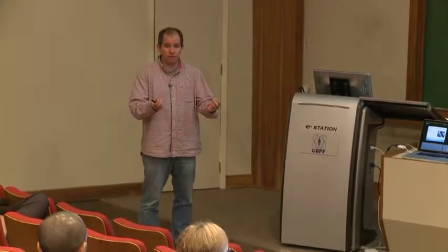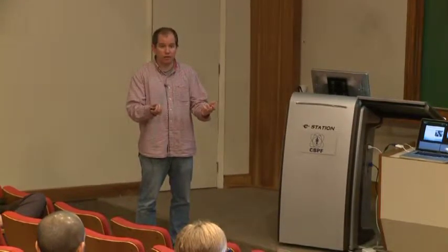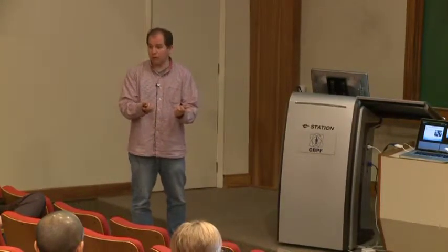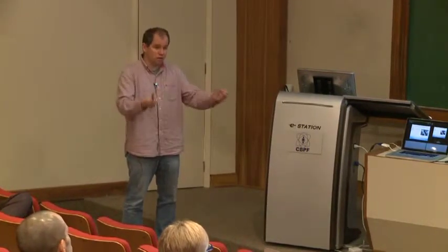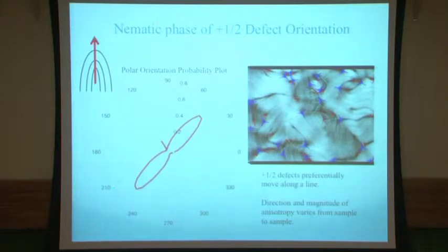That frequently happens in condensed matter physics. I can take defects and make a new kind of phase, right? Like a TGB twisted grain boundary phase is a phase that's organized by the spatial orientation of the defects. Here you have a nematic phase that's organized, it's a dynamical nematic phase, and it's determined by the spatial orientation of the defects. And so we were interested, well, is this just a fluctuation, or is it really a true phase?